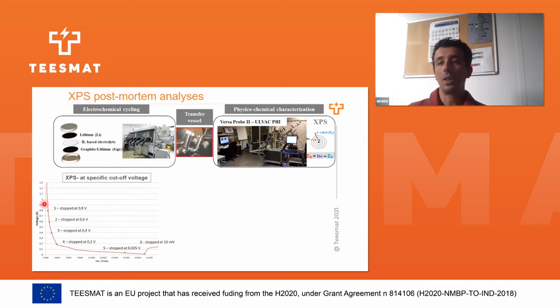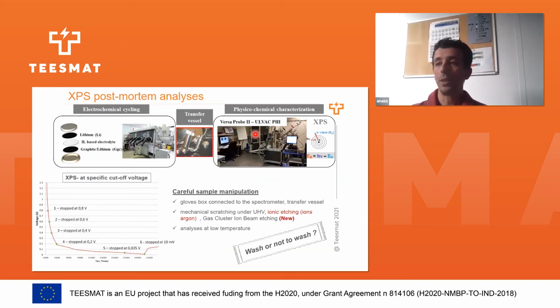And what we do, we stop the battery at different cutoff potentials. We open it in the glove box. We do some chemical surface treatment, like washing with solvent or not, transfer the sample to the XPS and do the analysis. For that, we need very careful sample manipulation.